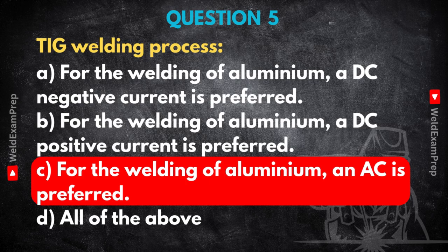Wow, it's amazing how the electrical cycle is perfectly matched to solve that material chemistry problem. What's the most obvious sign of failure if someone tries to ignore that and use the wrong current, say DC negative, on aluminum? What would an inspector see immediately? Oh, it's usually pretty ugly and obvious if someone tries DC negative. The biggest giveaway is a really dirty, contaminated-looking weld. You'll see dark, sooty deposits, maybe gray scum on the surface. That's basically the oxide layer not being broken down.